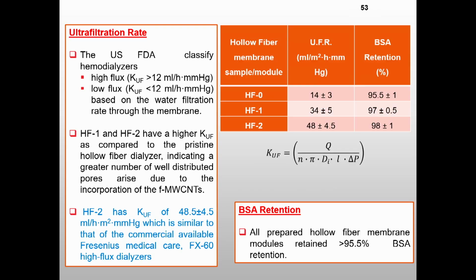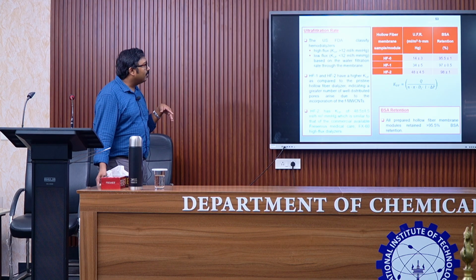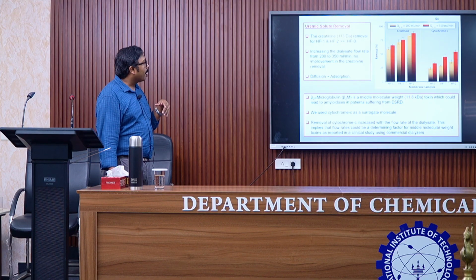Ultrafiltration: as the pore sizes increase, your ultrafiltration rate again increases. These are measured in ml per meter square per hour per mm of Hg, and you have 98% retention of bovine serum albumin. That means you had good clearance of solutes and good clearance of water, but your membranes could withhold essential proteins like bovine serum albumin. And so these are similar to what we have today in markets.